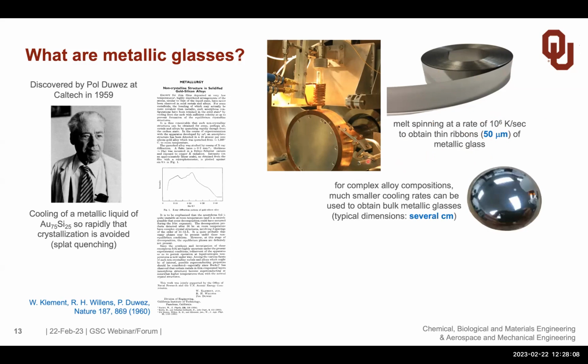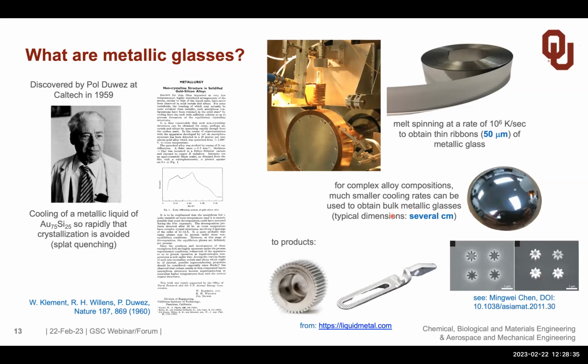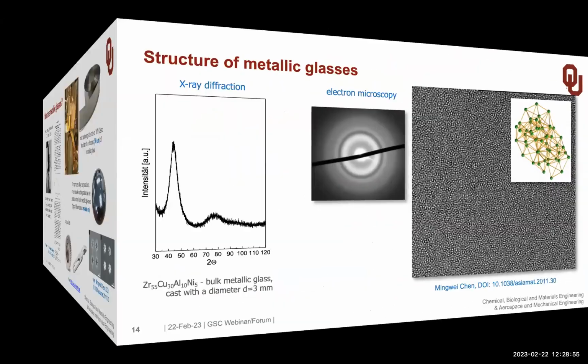And if you now go to more complex alloying compositions, so you go from binary or ternary to 5, 6, 7 elements, you can actually reduce the cooling rate tremendously. You go to a few Kelvin per second, and then of course you can make something several centimeters in size, which you see here, and these are called bulk metallic glasses. And that actually leads to products. You can make very nice high strength gears, or very small components in the order of a few microns. You can make golf clubs because they have elastic properties which are not possible in crystalline metallic materials. And then you would like to know the structure.